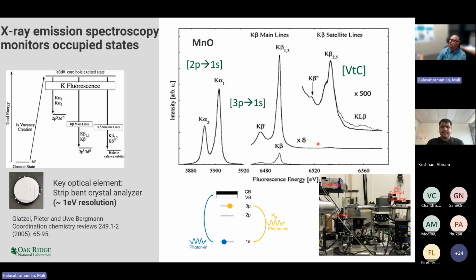About 500 times weaker, you can get emissions which come from these valence states. They're called the valence to core emission, and they give rise to these features which are called K beta 2.5 and K beta double prime. So these features are the valence to core excitation features, and because they come directly from the valence band or the valence orbitals, they are quite sensitive to bonding and to the nature of ligands that are surrounding the manganese.